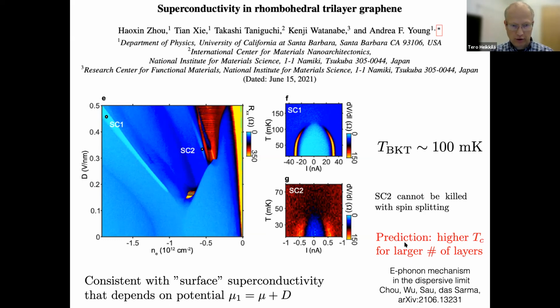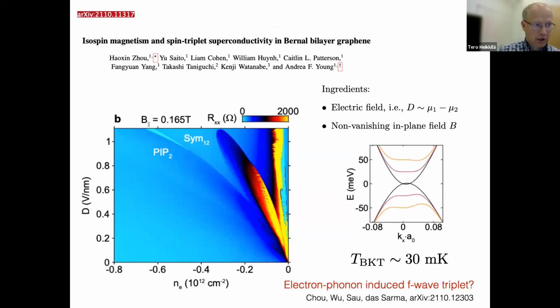And also there is a direct prediction that if you would go to a higher number of layers, you would increase the TC in this case. Actually, Dasarma and others took our approach and applied it to this three-layer case, including all the hoppings and also this electric field, and they basically find something on the order of this 100 millikelvin. They don't study the BKT temperature transition, only the mean field TC. There's another experiment, very recent, on now bilayer graphene.